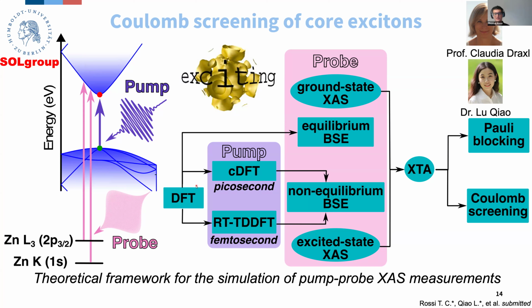And so the way the calculation is done is you always start from a DFT calculation. The DFT calculation gives you the electronic structure of the ground state of your material. Then once you have the DFT completed, you can run a Bethe-Salpeter equation calculation on top of it. That's the calculation that will deliver the ground state X-ray absorption spectrum that is measured experimentally. And then you want to do another batch of calculations where now you want to account for the effect of the pump excitations. And there are essentially two ways of doing this, depending on the time scale at which you do the experiment. One is on the picosecond. So on the picosecond, remember that your carriers have cooled down. They set up in a Fermi-Dirac distribution, for instance, with only a temperature that is much higher than the ambient temperature.